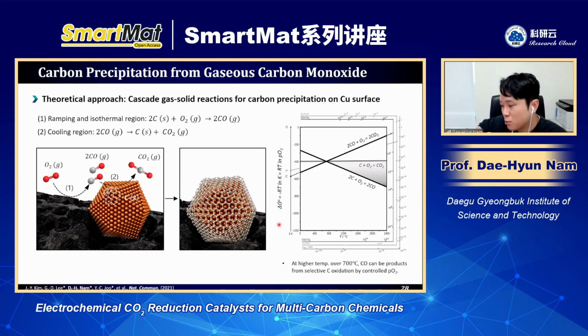It means that this carbon shell should be very porous, and this should enable some atomic and ion transport. So in that way, we wanted to fabricate this carbon shell by using a gas-solid reaction. This kind of reaction we call the Boudouard reaction. It means solid carbon can be precipitated from CO by the reaction with CO and CO2. So if we do some calcination using carbon and copper, we can get some CO and CO2 by the oxidation of this carbon.